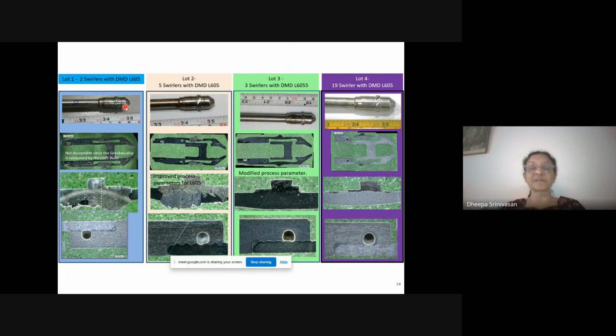They were throwing all these parts away into the scrap. And then these were experiments. The design of experiments was done by a student, an intern at DM3D, and they developed the process parameters, and in about 5 to 6 months came up with a perfect solution for this geometry, where they had to deposit a much harder lubricious metal, because it is going to undergo wear again when they put it back into the gas turbine.